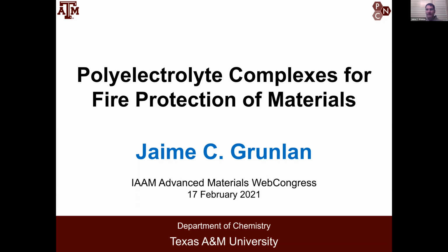Some of the ingredients that we use are shown over here at the right. You can see you typically have nitrogen-rich and phosphate-rich molecules which serve to create an intumescent type of treatment, which bubbles and creates an insulating char. Many times we also incorporate nanoparticles such as clay nanoplatelets to reinforce the char that forms during burning and stop fires. So it's a very flexible technology, but once again, people criticize the number of processing steps.